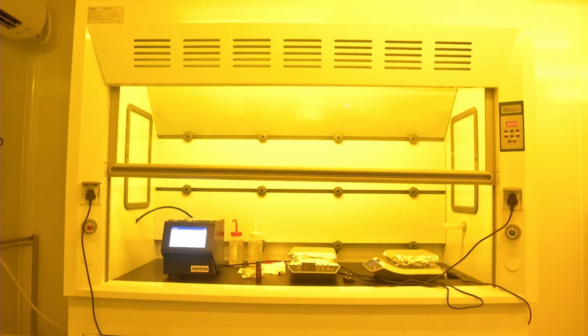We will spin coat the precursor on that, the polymer that we want to obtain as a flexible substrate, and then we will cure it at two different temperatures. And finally, we will show you how we can get a flexible substrate out of the silicon carrier wafer.